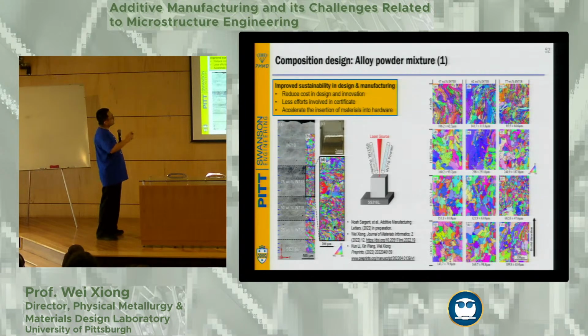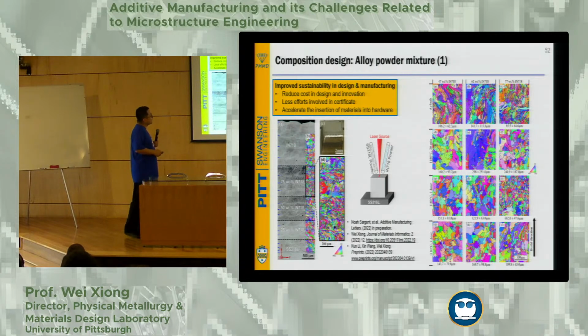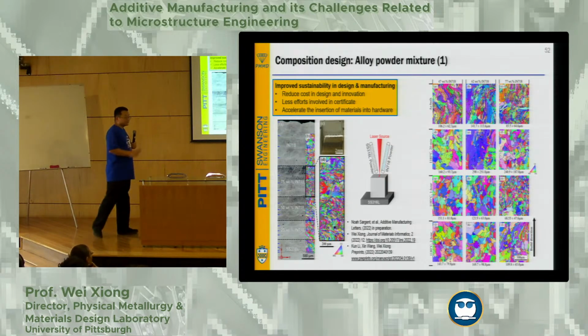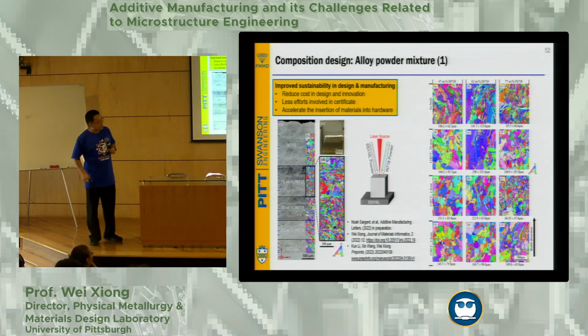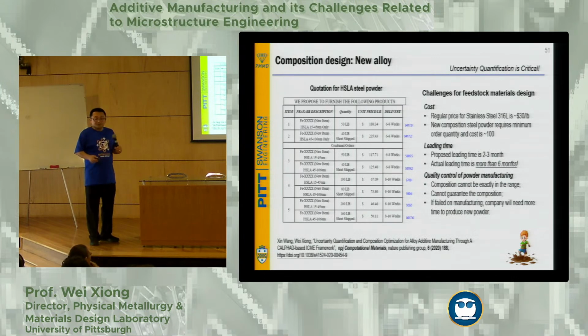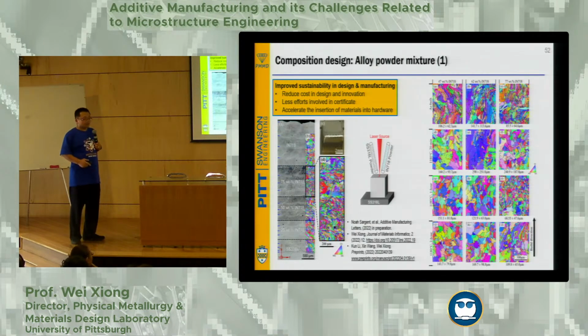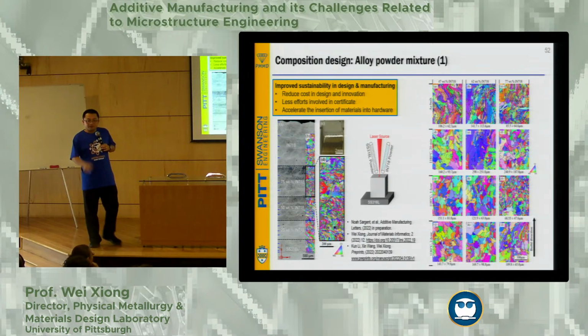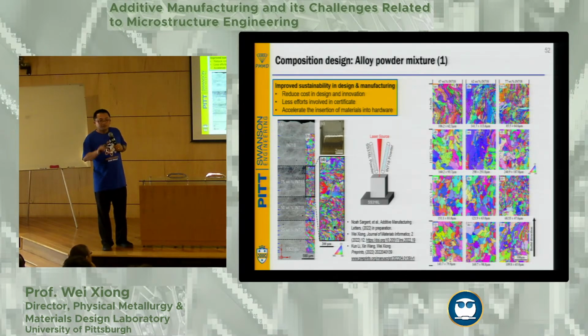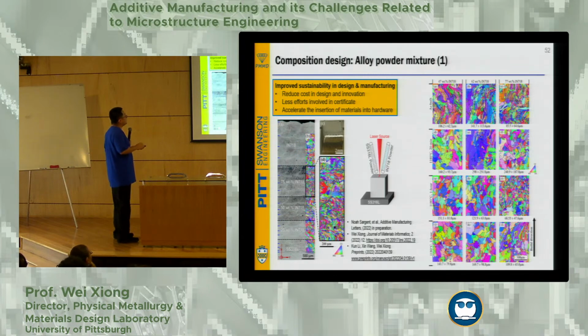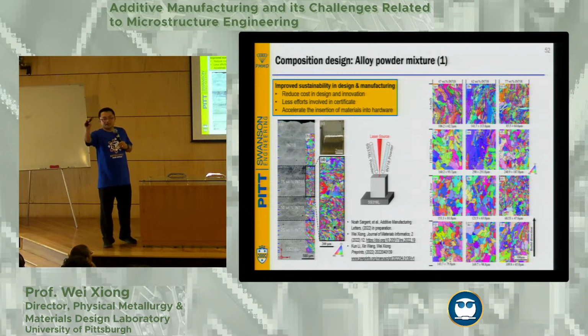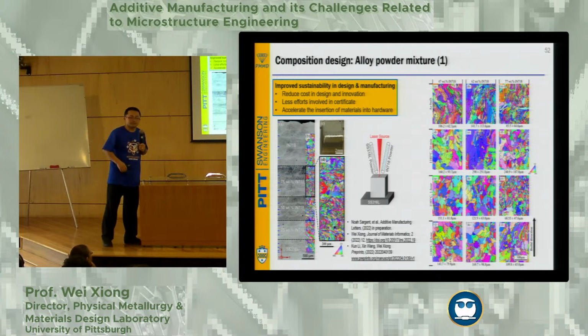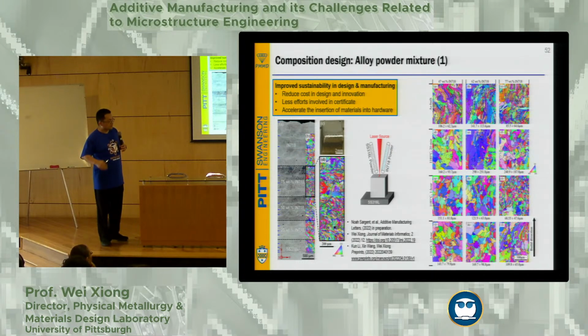But then we are actually coming through another direction. Our group made a lot of efforts about 5 years ago, because we got hurt by all of these issues. So what we do is, additive manufacturing is not only an engineering technique, but it can also contribute to scientific fundamental study. One of the things that we tested is using the directed energy deposition technique, right? This can allow you to print alloy A 100%, go to alloy B 100%. If you have multiple spray nozzles of the powder, you can study even more materials together, right?